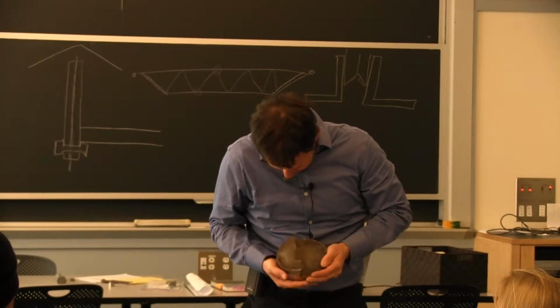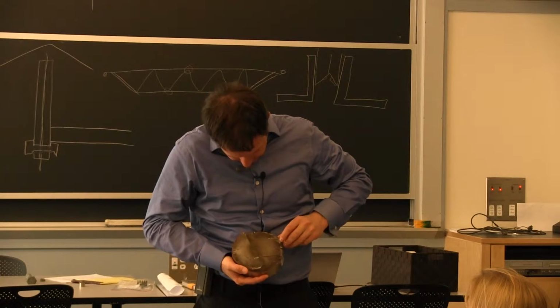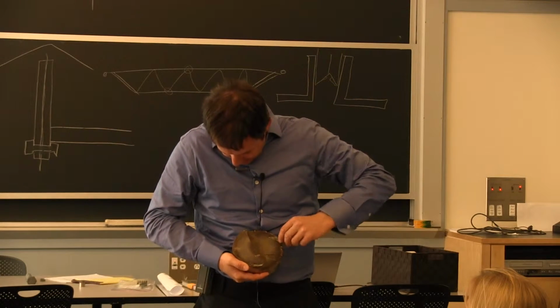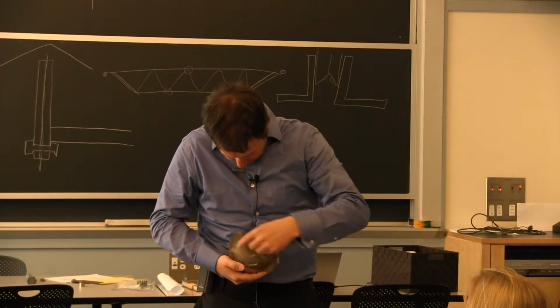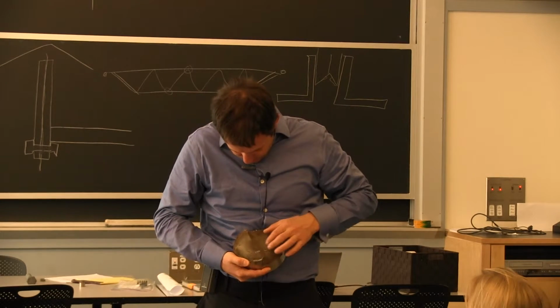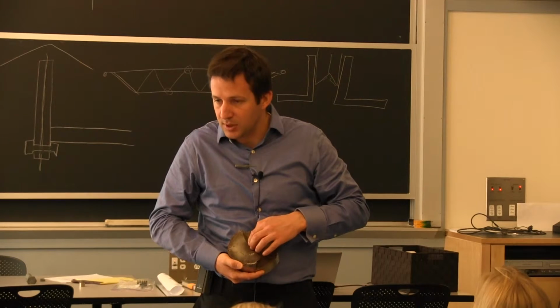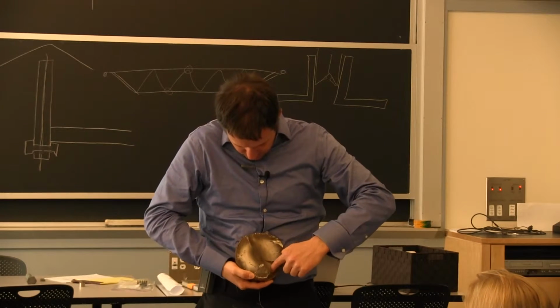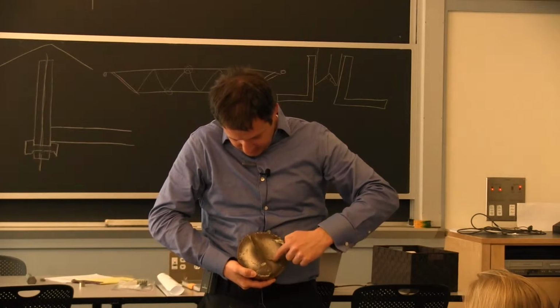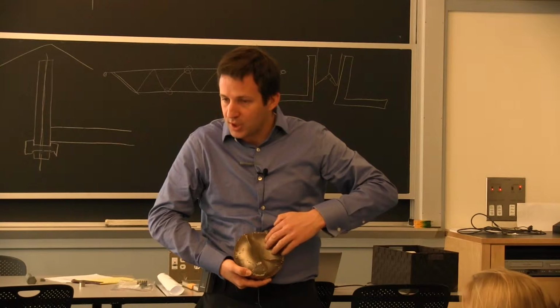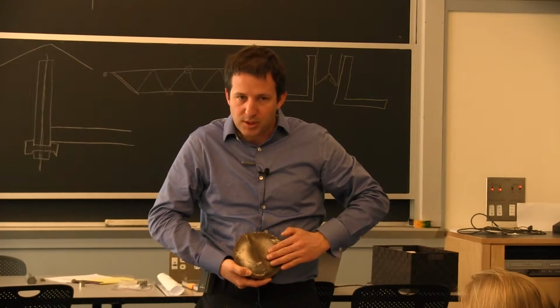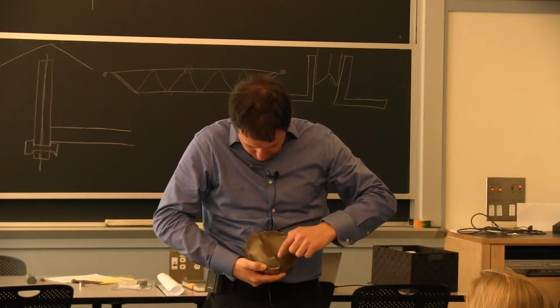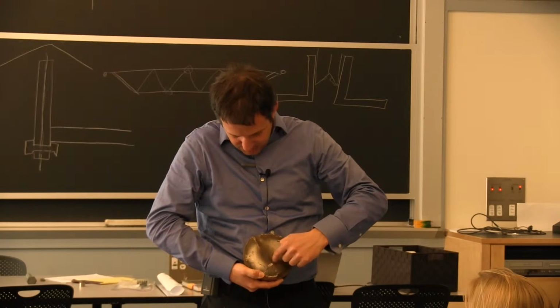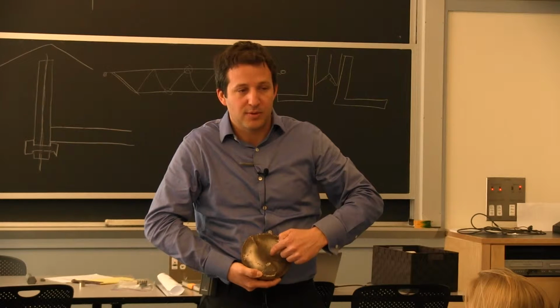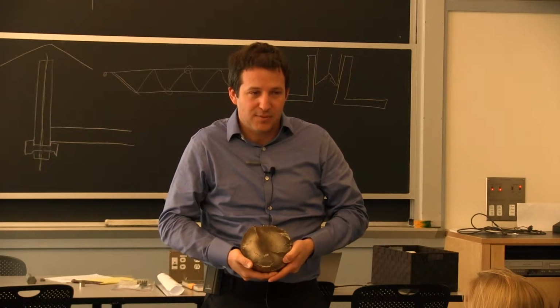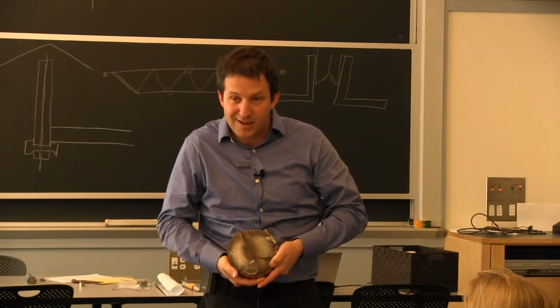What happened is there were multiple initiations. There's a crack that started right over here, and there was another crack that started on the very opposite side, and they pretty much met somewhere in the middle. You can see beach marks when you see these lines. This is where the crack was at a certain point in time. All of this was already cracked, up to the point where, to tell you the truth, this is the only thing you had left at the time of the failure.